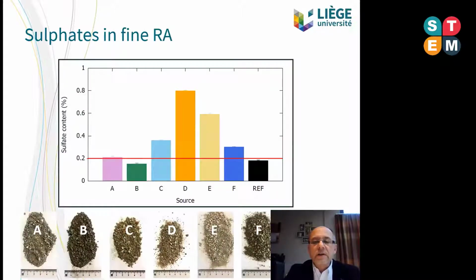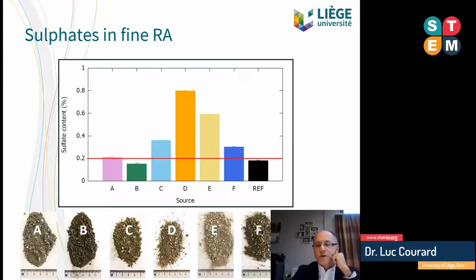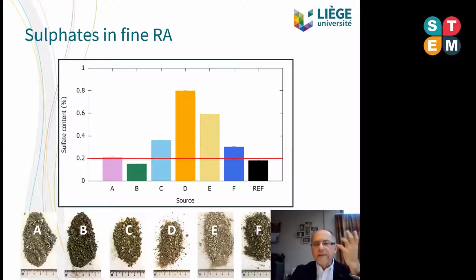We made an investigation on different recycling plants, and we took some samples to analyze the quantity of sulfate contents. Remember that the limit is 0.2% of recycled aggregates. So in some situations, we were above this value or we were under this limitation, depending on the type of recycling plant and depending on the type of material which is coming to these recycling plants. Of course, concrete coming from roads construction doesn't contain a lot of sulfates, while concrete coming from houses is contaminated with larger quantities of this material.